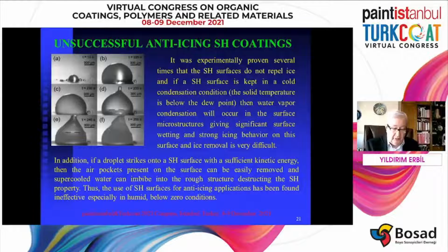And if a superhydrophobic surface is kept in a cold condensation condition, and the solid temperature is below the dew point of the medium, then water vapor condensation will occur in the surface microstructure, giving surface wetting and strong icing behavior on the surface. Also, many articles have been published on anti-icing superhydrophobic coatings. In practice, their success is very limited.